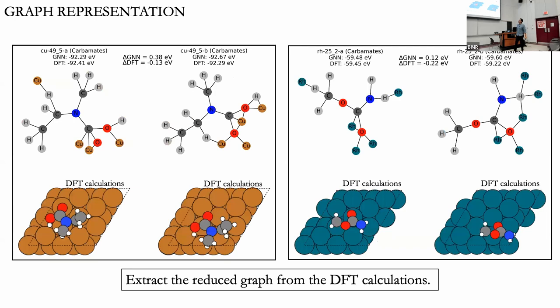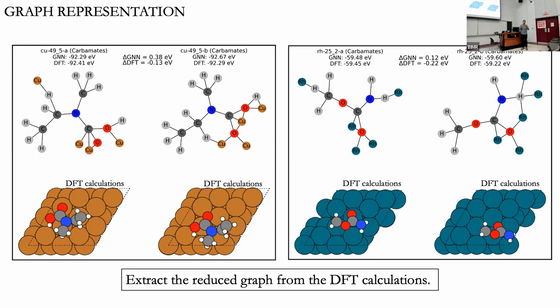We have 3,315 total pairs of adsorbents and metals, composed of all possible interactions of 207 closed-shell organic molecules and 14 different metals, split into nine families. For all calculations we considered three different crystal structures for the metal — we didn't want to be biased toward any specific crystal packing. All calculations were done with DFT using PBE and dispersion corrections. The difference in energy between the adsorbent-on-metal and the bare metal follows a unimodal distribution — almost Gaussian for all families — which backed up our hypothesis that this is what the model should be learning.